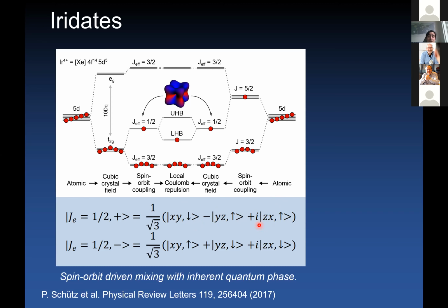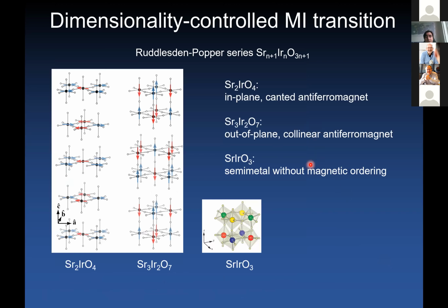because as you know from your basic quantum mechanics, if you have wave functions that are characterized by a superposition of a real and an imaginary part, then when you are performing adiabatic evolution in configuration space, in addition to the usual trivial phase factor, the dynamical phase factor, you will also pick up a geometric phase factor or a Berry phase. So the presence of this inherent quantum phase causes your system to acquire a finite Berry phase during adiabatic evolutions, and this can give rise to topological phenomena in these materials. So these iridates are a good place where we find both Coulomb repulsions and the possibilities of topological behavior. So they're worth investigating at their interfaces.